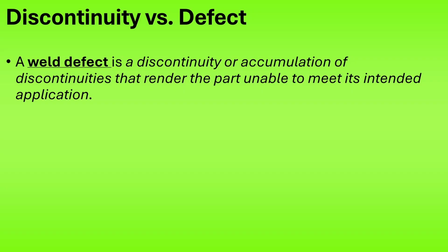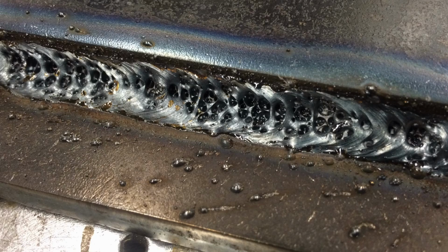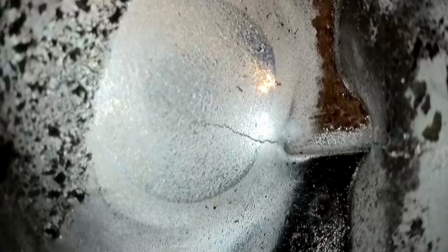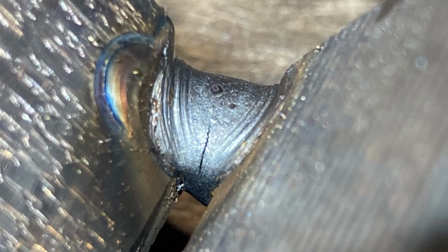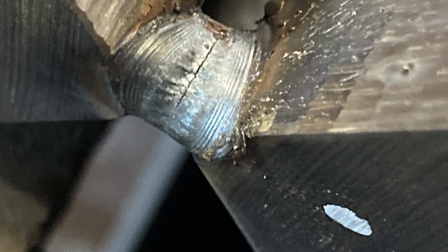And that brings us to the term defect. A weld defect is a discontinuity or an accumulation of multiple discontinuities that render the part unable to meet its intended application. And thereby, those discontinuities make that weld defective. So, while a little bit of porosity is okay, too much porosity would render the weld unusable, and that porosity would have to be removed and the weld would have to be replaced or repaired. And one discontinuity is almost always considered a defect, and that's a weld crack. Any cracking in the area of a weld or the heat affected zone could be considered a defect because they grow.